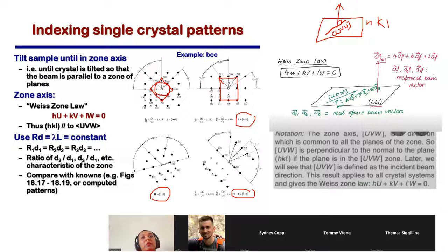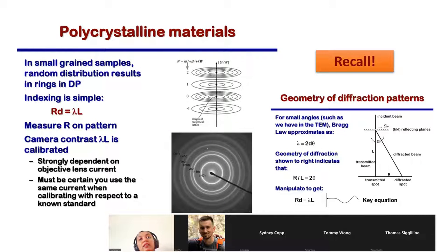And then the second point here, the second circle here, would be the diffraction coming from the second point and giving me the second D. So you see that I created two circles here. And why was there a need of creating these circles? You get these points if it was a single crystal, but in the polycrystal, these points are also connected because these points, which are at the same distance, are coming from all the other polycrystalline planes. So that is why we get a feature like this.